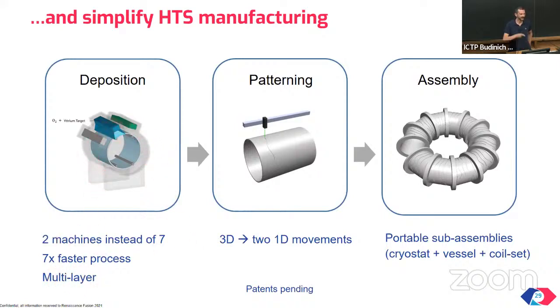As a matter of fact, we deposit a stack of many layers of HTS intertwined with the other layers that I mentioned before. This multiple stack is our equivalent, more elegant, I would argue, of winding multiple times the tape or the cable to make the coils. We just deposit multiple layers, one on top of the other.